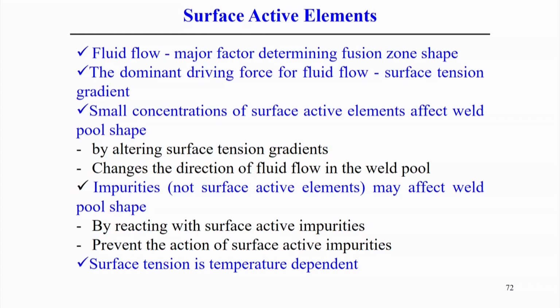So, you know in welding process that apart from the conductive heat transfer that actually happens within the weld pool, there is a considerable amount of material flow, or fluid flow, within the weld pool. In that case that fluid flow actually takes a major role to determine the fusion zone shape, and in most of the cases we normally neglect this fluid flow effect, and always try to do the heat transfer analysis by using only the heat conduction that happens within the weld pool.